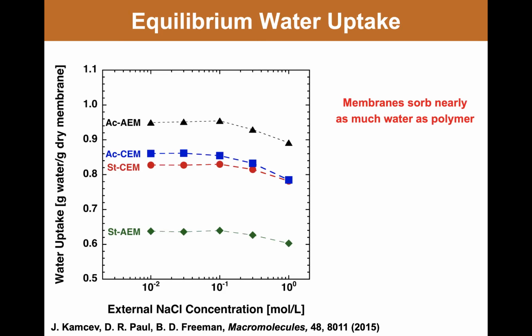One of the most important characteristics that governs transport in such membranes is the water uptake. It turns out to be very important for both ion sorption as well as ion diffusion. You'll remember that Yasuda postulated that the water content in his uncharged membranes was proportional to free volume, and he correlated the salt transport over 5 orders of magnitude in diffusion coefficient simply with water uptake. So we'll measure water uptake almost before any other property when we're seeking to do fundamental studies on ion exchange membranes.